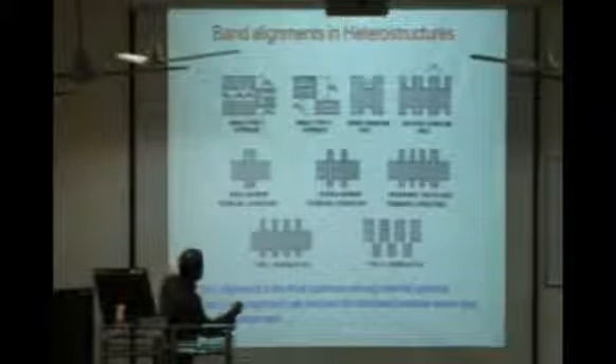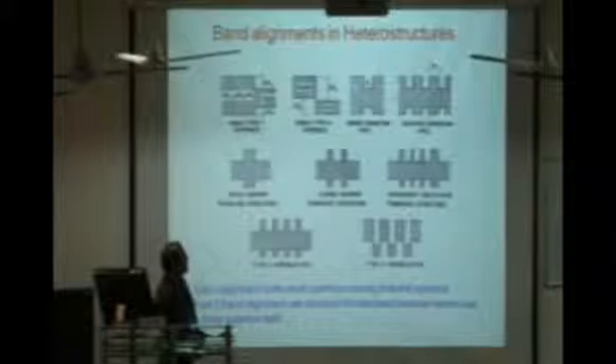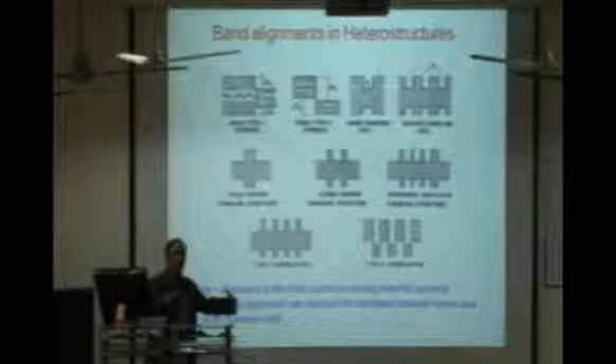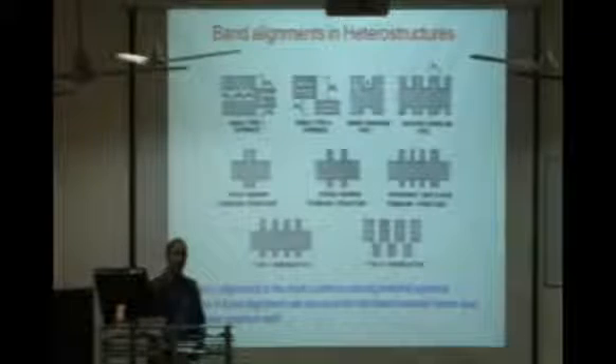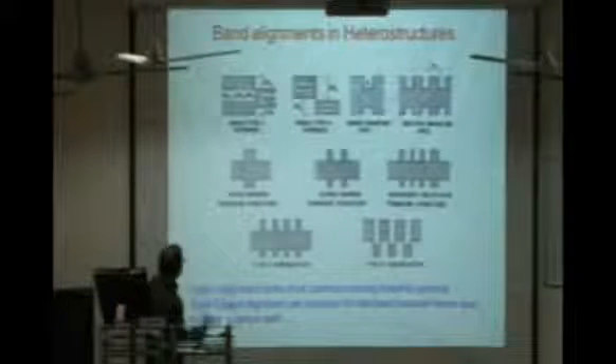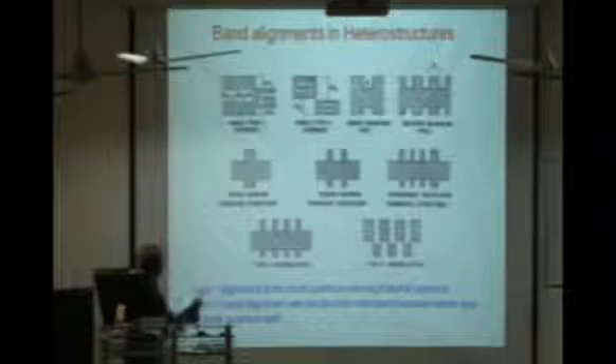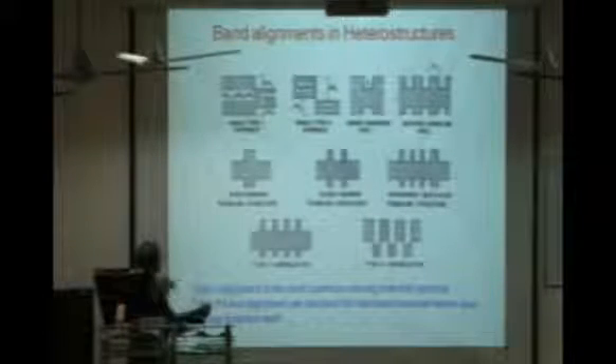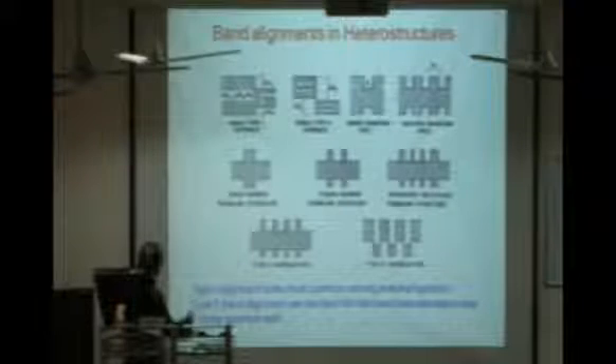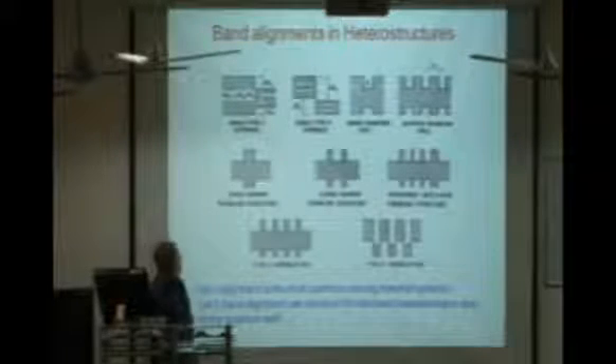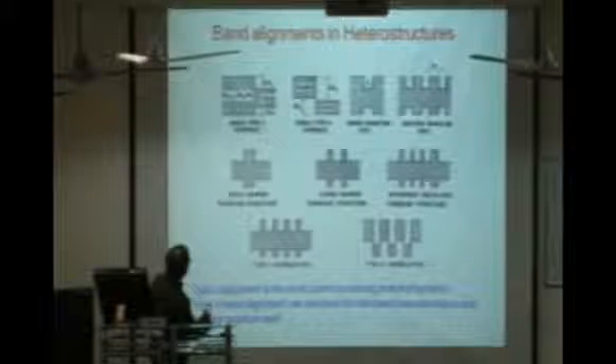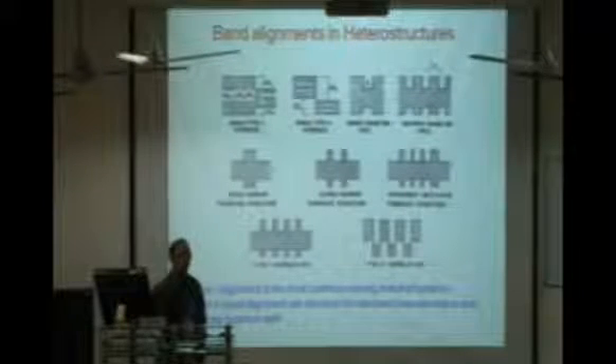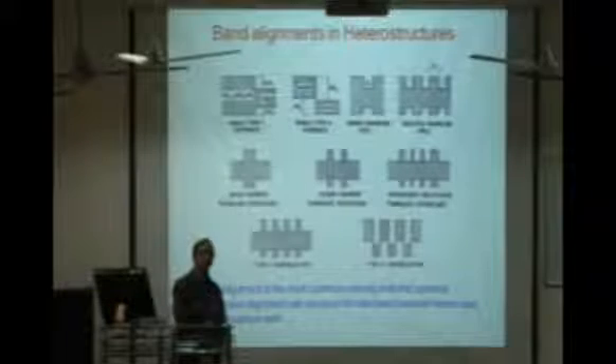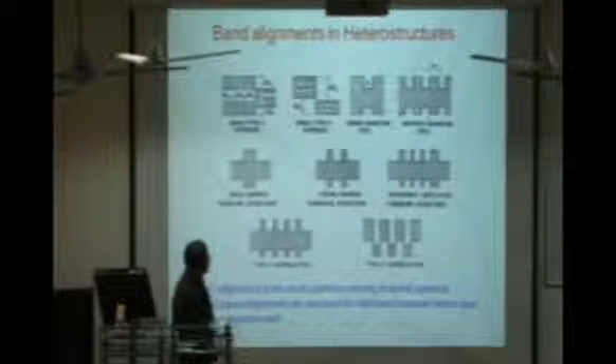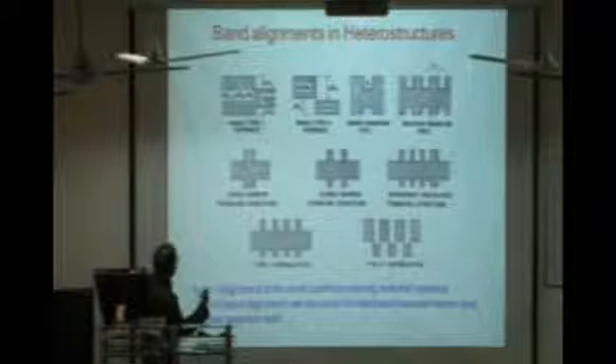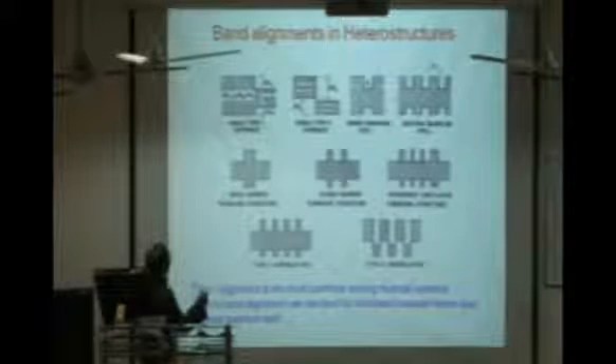If I repeat the structure, we actually get multiple quantum wells. Now, these quantum wells can be well separated, so they do not interact with one another, or they may couple with one another. In fact, if I just use this one and repeat it more and reduce the spacing between them, what we call it is a superlattice. Since this is a type 1 heterostructure, we call it a type 1 superlattice. So we get new and unique properties in the dispersion relation in the case of a superlattice, which I'll show in the next slide. And another possible band alignment in heterostructures can be type 2.